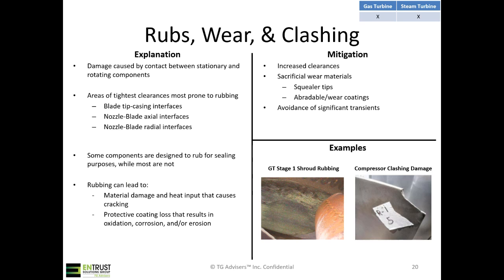The next failure mode is rubs, wear, and clashing. It's damage caused by contact between stationary and rotating components. Obviously, it's a bad idea to have rotating components hit static ones. It's typical on areas of tightest clearances. Those are going to be the areas such as your blade tip to casing interfaces. There's also going to be your nozzle to blade axial interfaces and radial interfaces. Sometimes this can even happen with the rotor portions of the turbine.